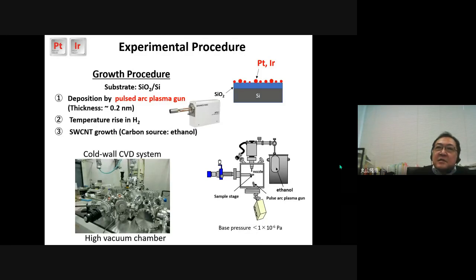This shows the experimental procedure for carbon nanotube growth with platinum group metal catalysts. We formed catalyst particles on a silicon dioxide silicon substrate by the pulsed arc plasma deposition. It formed nano-sized metal particles on the substrate.